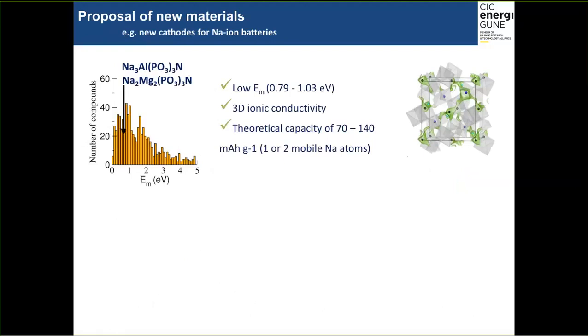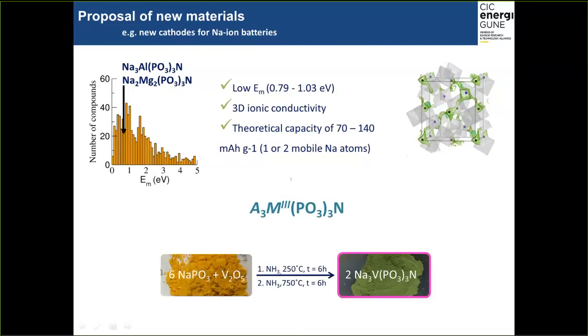But once we have a list of screened compounds by ranking of migration energies, we can also try to propose new potential materials by structural similarity. So, for example, in our list, we found two materials with relatively low migration energy, 3D conductivity, and interesting theoretical capacities with up to two sodium mobile ions in theory. So from here, we have identified these compounds that can be interesting.